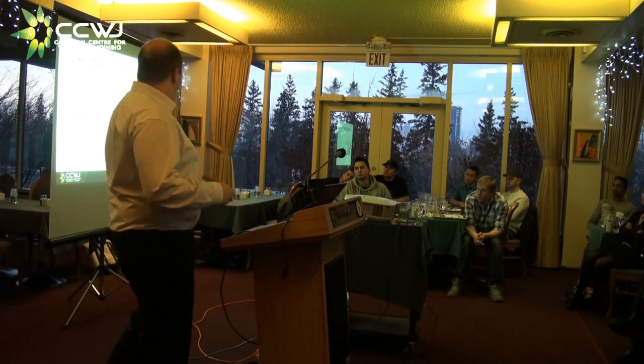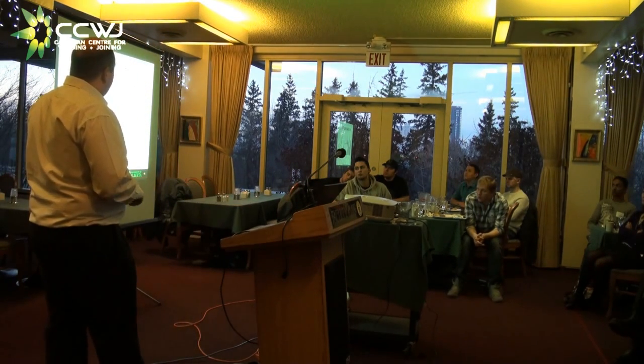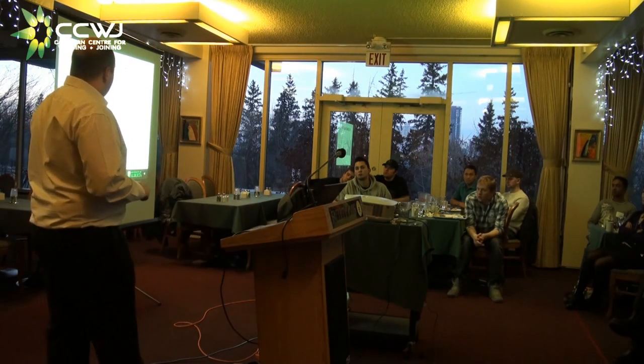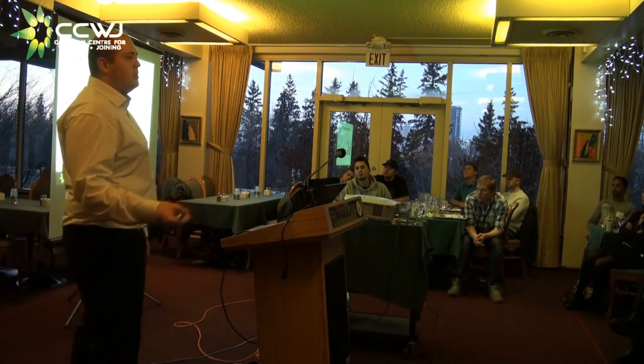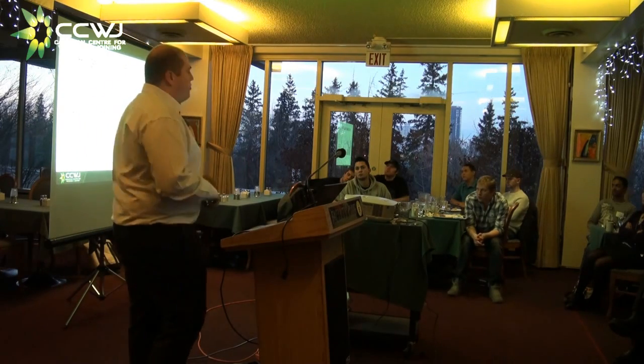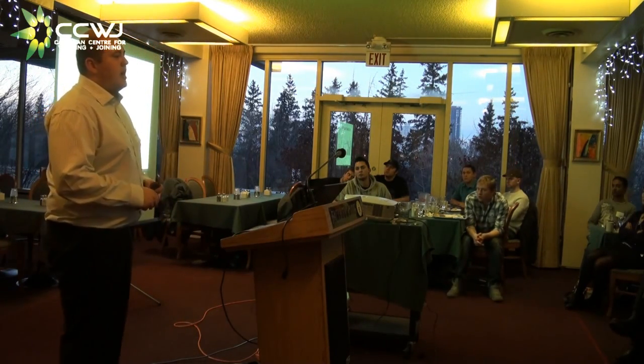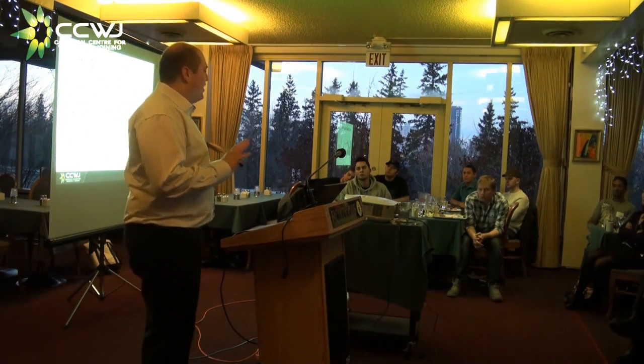Interesting to note is that we are exceeding deposition rates of the current PTA process. PTA, anywhere between 8 to 10 pounds an hour. Well, the hot wire MIG in its initial development stages that we're at is already outperforming in terms of deposition rate. Now, I say 8 to 10 pounds an hour for PTA. I know there are guys in the province doing higher deposition rates. This is just the data I have, so if you're doing higher deposition rates, I don't mean anything against you. This is just the data I got, so I'm running with it.